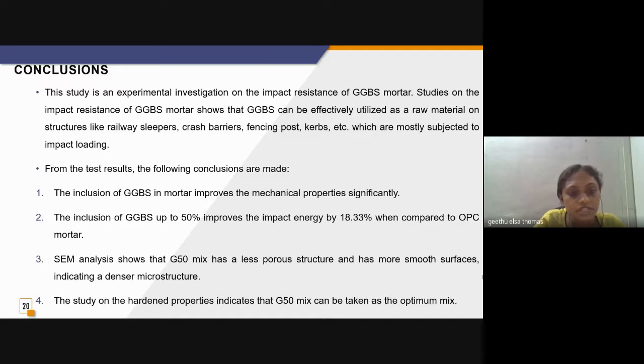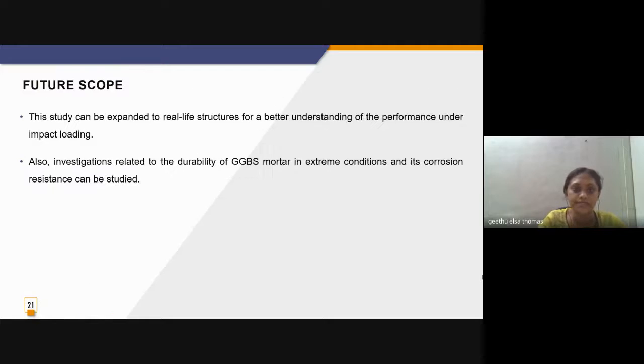The inclusion of GGBS in mortar improves the mechanical properties significantly. The inclusion of GGBS up to 50% improves the impact energy by 18.33% when compared to OPC mortar. SEM analysis shows that the G50 mix has a less porous structure and more smooth surfaces, indicating a denser microstructure. The studies on the hardened properties indicate that the G50 mix can be taken as an optimum mix.